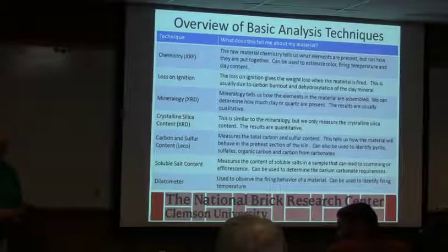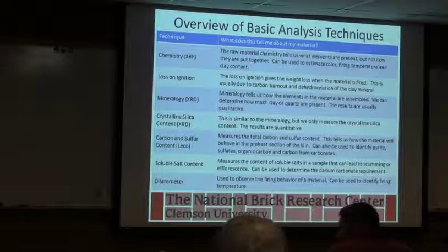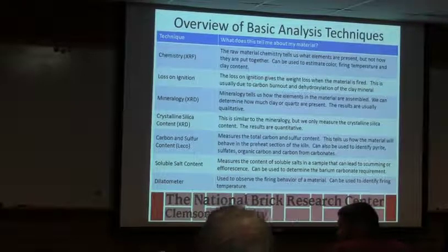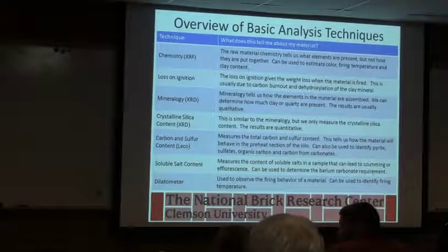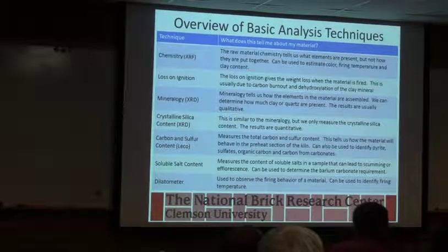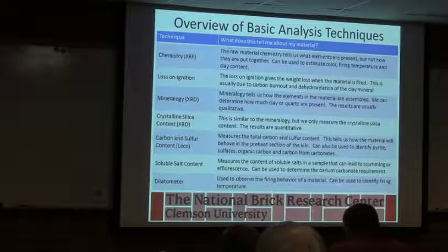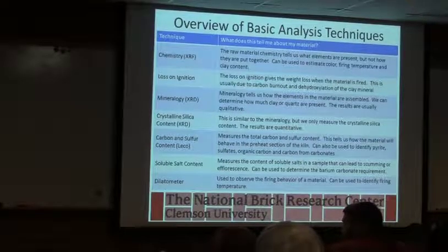So when we do our absorptions coming out of the kiln, we do a top, bottom, on the top, on either side, and in the middle. Add like 5%, 5%, 4, 5, 5, and then 1 in the bottom middle. Oh, 1 in the bottom middle? Yeah, 1. I'm assuming that would have to be, is it a top-fired kiln? Yeah, top part. Okay. Does that seem like you're penetrating pretty deep with the heat? So it would have to be how you're putting the heat in the kiln. So the top part would be put right down at the bottom? So I'm guessing it's near a firing lane.